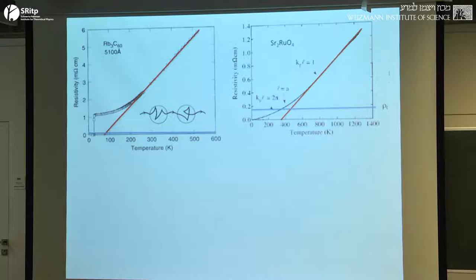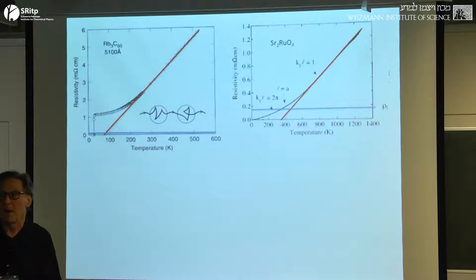To give you an idea of how wedded people are to Boltzmann transport theory, this little cartoon is from this paper where they pointed out, without the least bit of embarrassment, that the mean free path that they extract from this is about 1 angstrom, whereas the single unit cell, that is to say, the single C60 molecule, is, I can't remember, 7 or 8 angstroms apart. So they have this nice cartoon of the electron scattering many times within a single molecule.